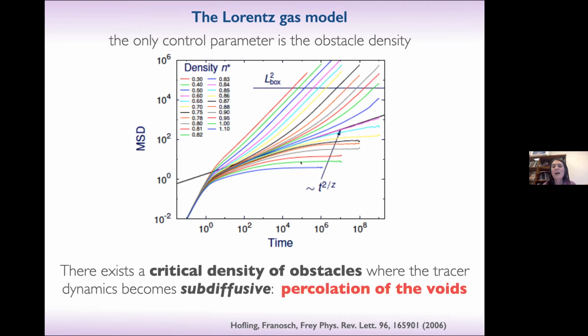Instead, if you have too much packing fraction, too large an obstacle density, the void space is not continuous and does not percolate, so you will have islands in which your intruders can move, and so they will become localized. And then there is a critical packing fraction of the obstacles at which there is this percolation of the void transition, at which the tracer dynamics becomes subdiffusive. This is well known, and the exponent can also be calculated, and it's been calculated in this work.